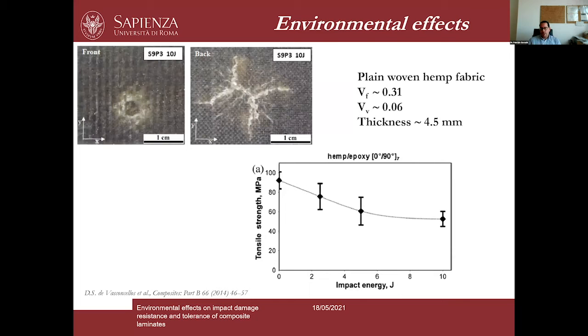And if we combine the effects of environmental aging with low velocity impact, we can expect some, I would say, very bad results for natural fiber composites, simply because natural fiber composites do already show lower impact resistance compared to synthetic fiber composites. And here, for example, you can see the results for a composite material based on epoxy reinforced with a plain woven hemp fabric. And as you can see here, when we performed tensile strength tests after an impact, even an impact at low energy, 10 joules, you can see that the decrease in the mechanical properties can be pretty significant. So let's imagine what happens if we combine environmental aging with the low velocity impact on a natural fiber composite.